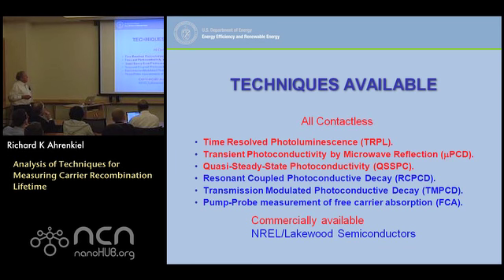It's really the same kind of thing you do with contacts, except rather than painting contacts, he has a coil. I think they run about 10 megahertz pickup, and they flash a long duration, like milliseconds long, and they look at the photoconductivity, and then they use algorithms to extract carrier lifetime out of that. This is the mainstay of the silicon wafer industry, I would say. It's quite cheap, and everybody quotes QSSPC.